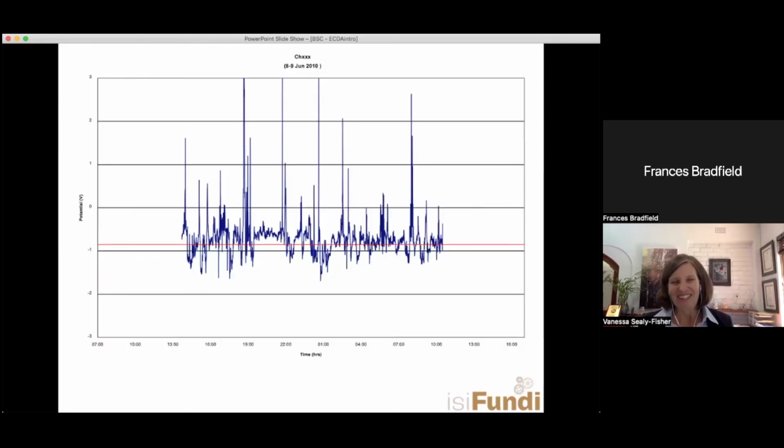I do. Yeah. And here we go. We're looking at very positive excursions here. And we are not protected at all. As you can see, red line is protection. So in general, we're not even protected over there. Here we are actively corroding our pipeline if there are any defects. And we need to sort these excursions out as soon as possible. So areas in which you have positive excursions in your stray current survey are big issues if you have the other risk factors.